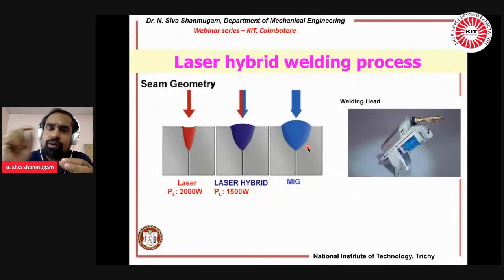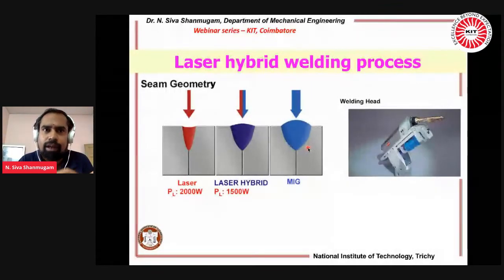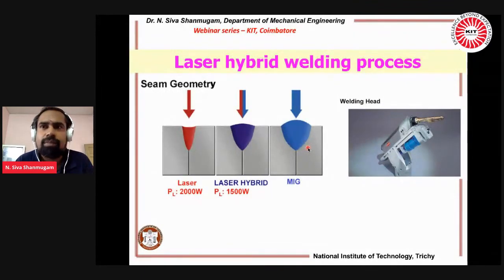So the power and current. When you go for finding out the power, it is current into the voltage. If you are operating with 60 amperes, and the voltage is something around 10, 60 into 10 is about 600. That is the power. In the laser, we are using the beam power. In commercial arc welding, we are calculating voltage into current. Voltage is 10 volts, and amperage is about 60 amperes. 60 into 10, totally 600. You are concentrating the 600 to a 10 mm diameter.